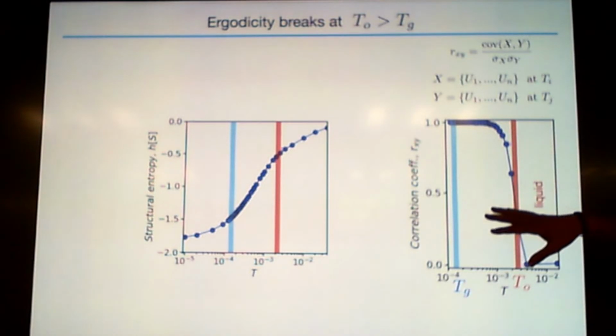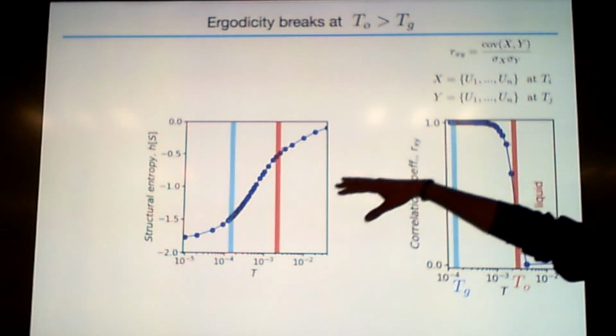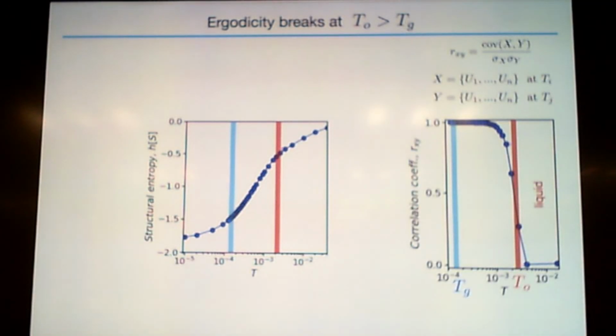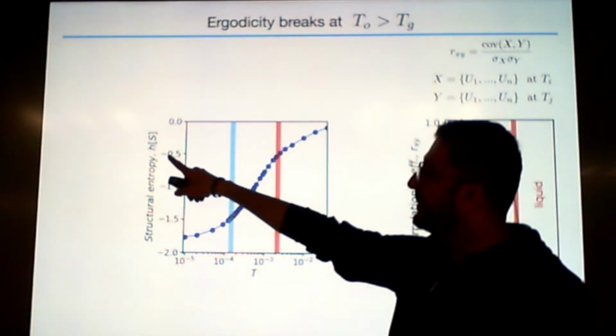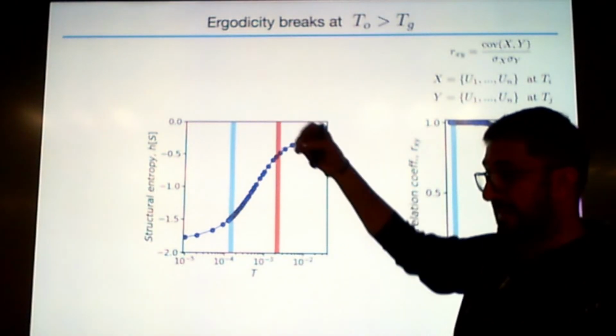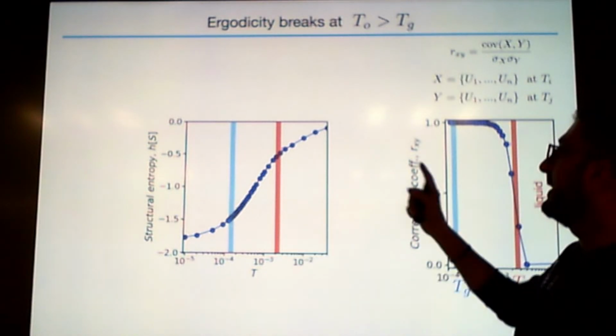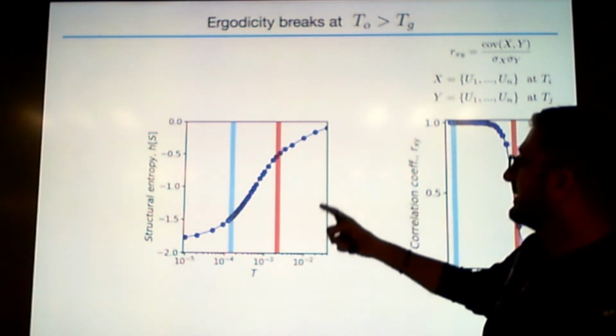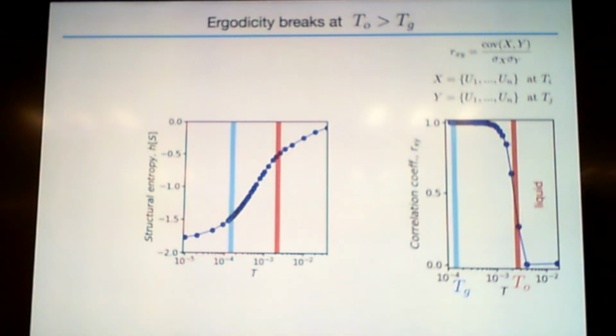why is it easy to measure? Because we have the structure factors, we just plug in. That's the entropy. Well, in fact, this is the structural entropy difference, the excess entropy. This is the difference to the ideal gas. So in the limit of T to infinity, it goes to 0. So the ideal gas has the same entropy as the system with infinite T.